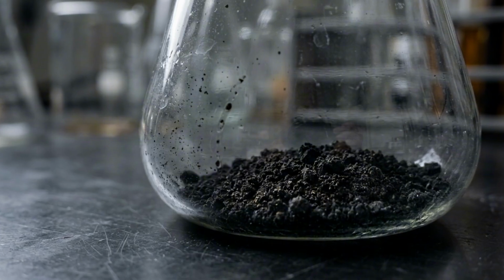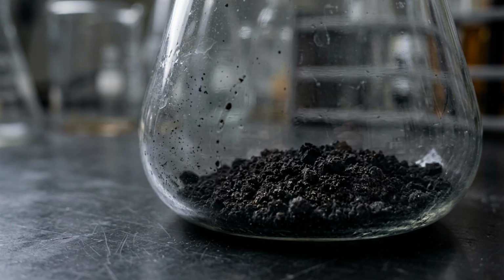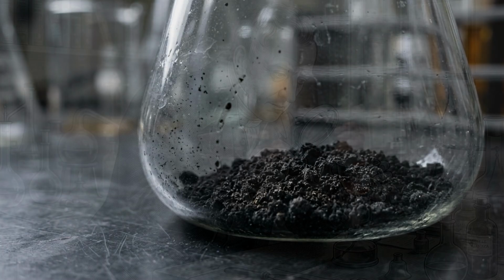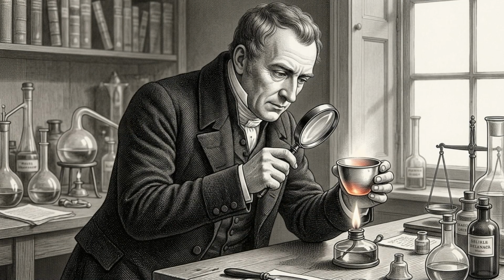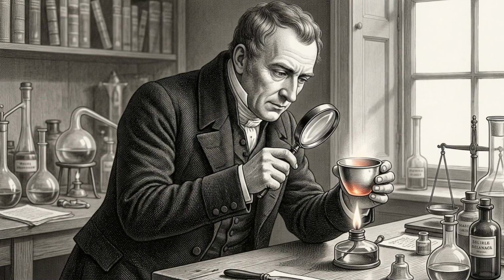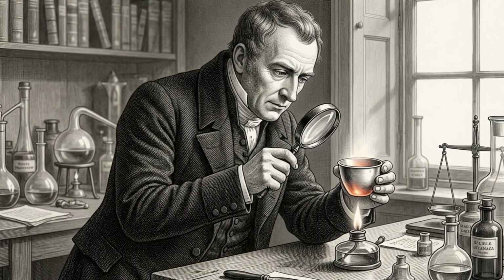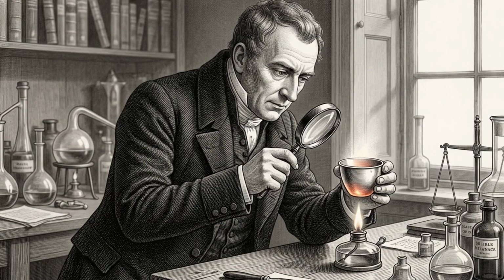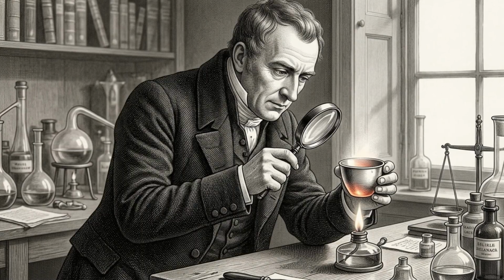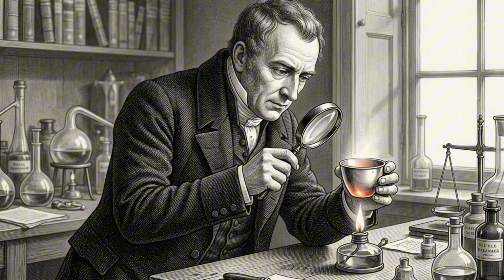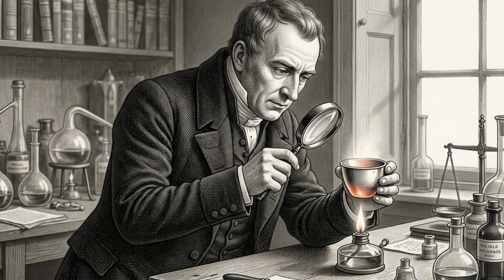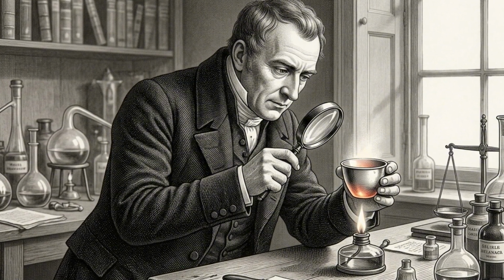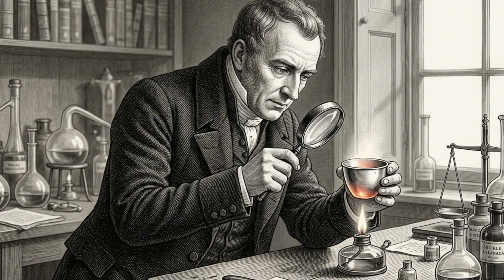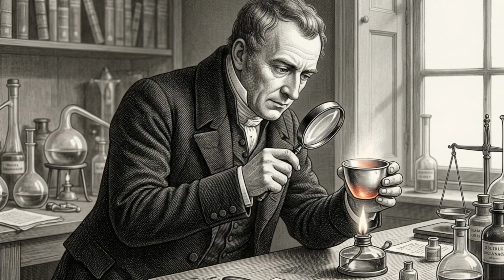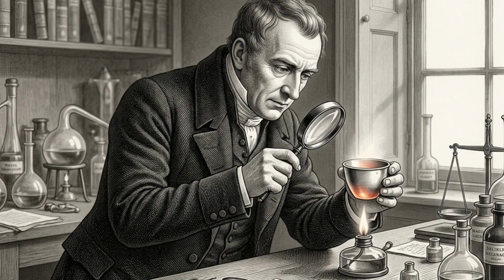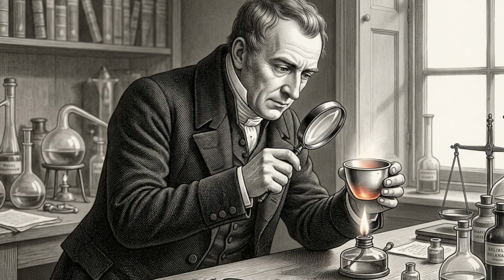This fuming combination of concentrated nitric and hydrochloric acids is capable of tearing apart the atomic bonds of gold, dissolving the solid metal into a liquid solution. Iridium, however, represents a thermodynamic wall that even aqua regia cannot breach. If a solid bar of iridium is submerged in a boiling bath of this highly aggressive acid mixture, the acid will have absolutely zero effect.